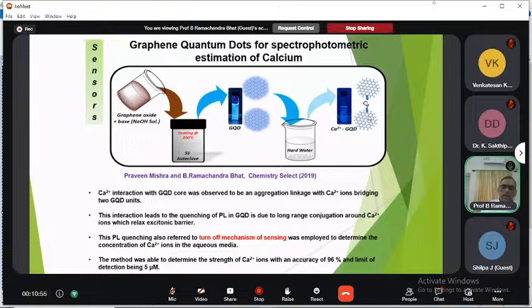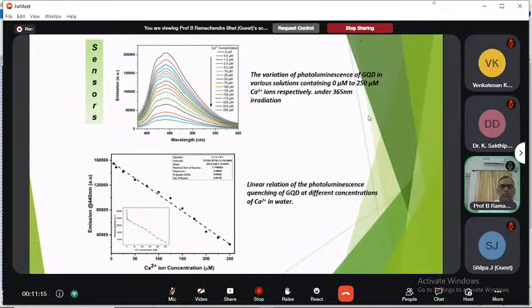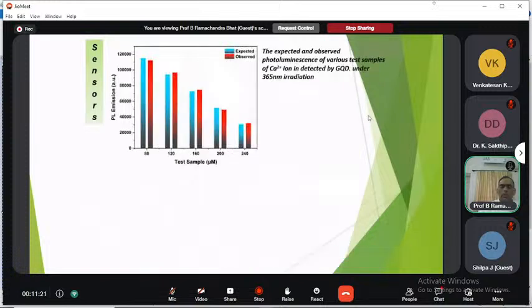It's called a turn-off mechanism because the PL quenching takes place, and it's employed to determine the concentration of calcium ions. The method was able to determine the strength of the calcium ions with an accuracy of 96%, and the limit of detection is 5 micromoles. So this is the extension of that same work, and the quenching of PL is because of the relaxation of its excitonic barrier, and this is used in practice.